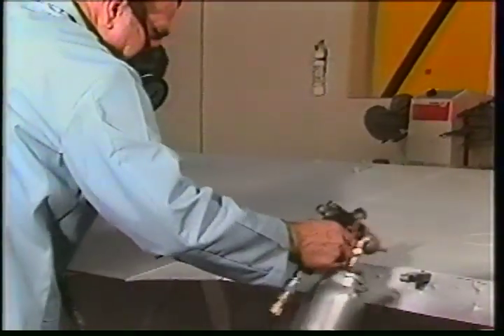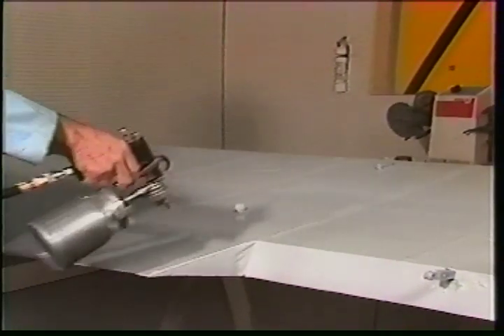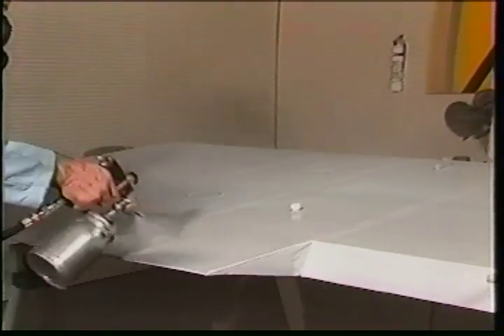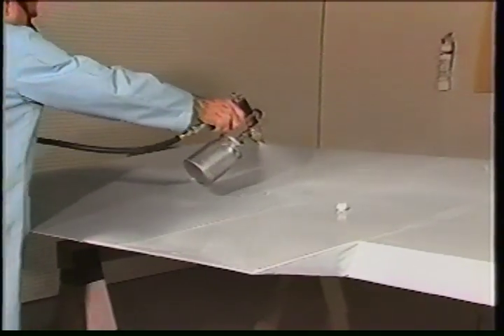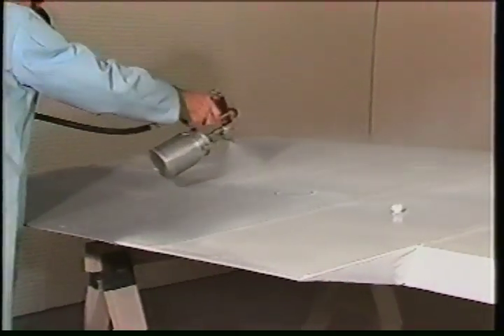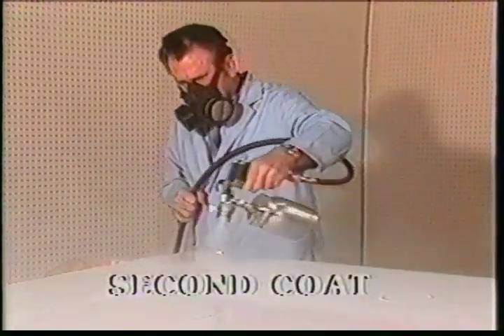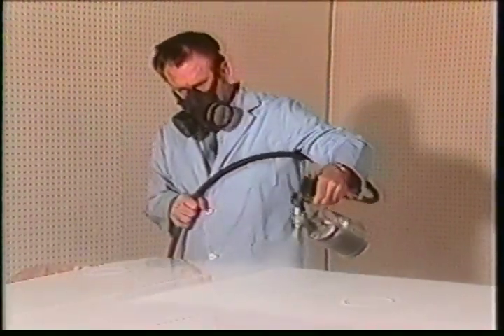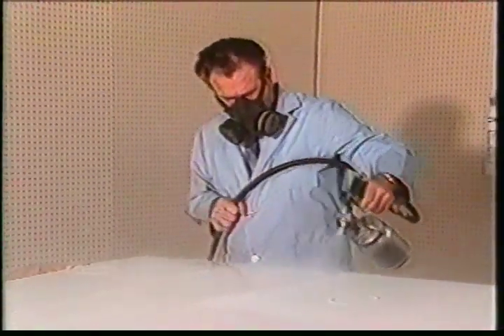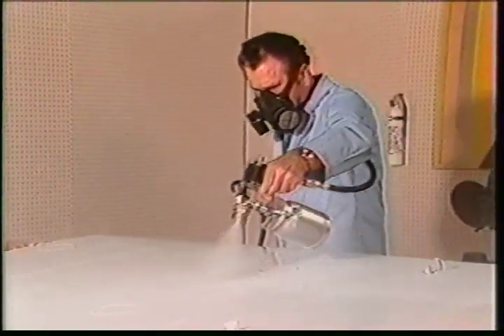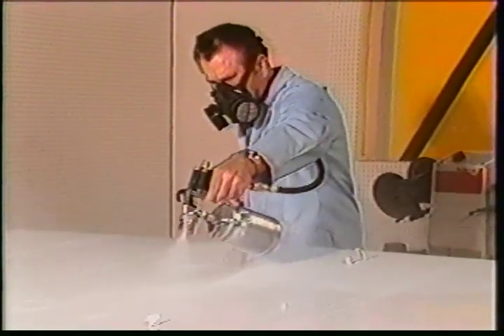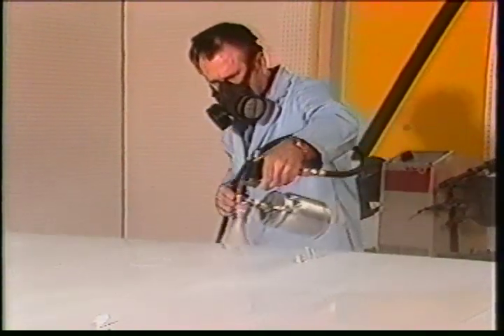There is a long list of mistakes that can be made by any inexperienced painter when using any coating product, and the Polyfiber manual offers many suggestions to avoid mistakes during fabric covering and when painting fabric and metal aircraft. If a very smooth hand rub finish is the goal, Polytone may be lightly wet sanded with a 400 grit or finer sandpaper between coats after drying 2 hours or longer. Coarse sandpaper will cause sanding scratches which may telegraph through the final coat. After sanding, the surface should be washed with clean water and wiped dry with clean rags or paper towels to remove any sanding residue. Repeat the tack rag cleaning before the next coat.